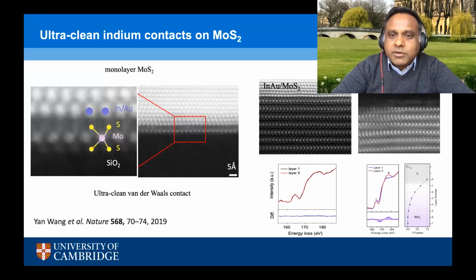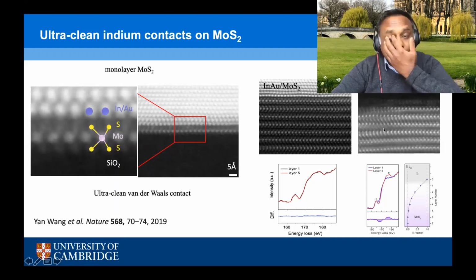And so since the interaction between the sulfur atoms in MoS2 is van der Waals, we're also claiming that the interaction between the metal and the sulfur is also a van der Waals type of interaction. In contrast, for comparison, if you take something like titanium and deposit it directly on MoS2, we find that there is a substantial difference in the EELS spectra, and one can also visually see that there's quite a bit of damage as well.